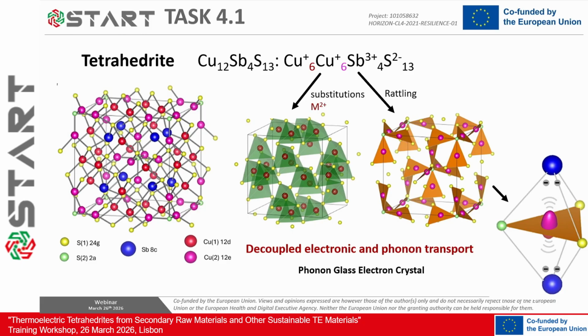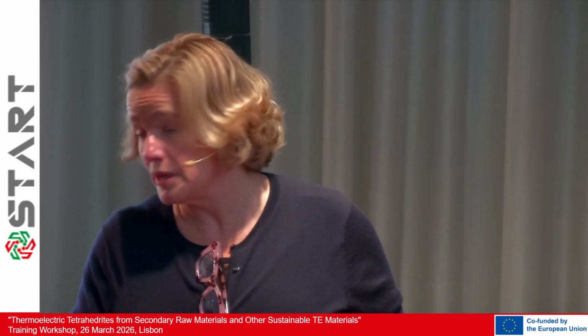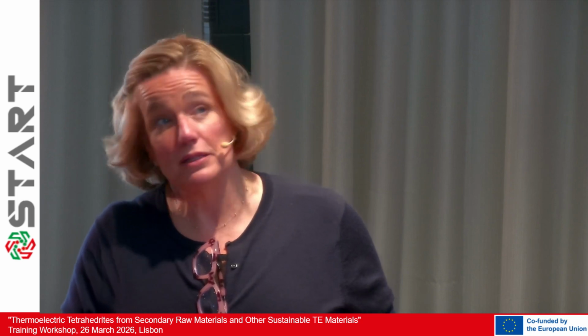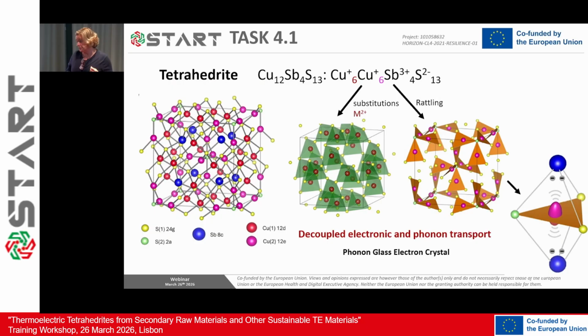When we substitute copper with 3D metals, which typically are 2+, this has been verified by neutron studies - they tend to substitute copper in these sites, which are the position 12d. This is very important because then we are letting the other coppers, which rattle between two atoms of antimony that have lone pairs repulsing the copper, vibrate in this plane. By doing so, it's very efficient in scattering phonons.